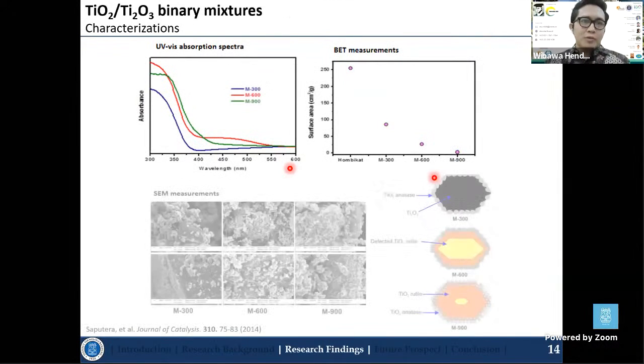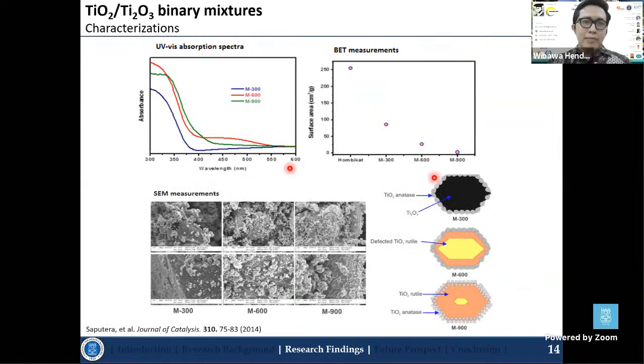So based on the UV-vis absorption spectra, it can be seen that the M600, or the mixtures that calcine at 600 degrees C, which is the yellowish powders, it gives the strong absorptions in the visible light regions. So based on the BET measurements, it can be seen also that by increasing the temperature of the calcinations, it decreases the surface area. And based on the morphology from SEM measurements, fish skin-like structures in M600 samples can be seen, which is incorporated of the titanium 3+ defects in the titanium dioxide photocatalysis.